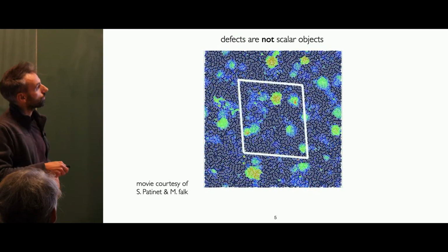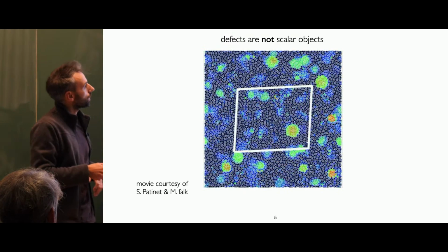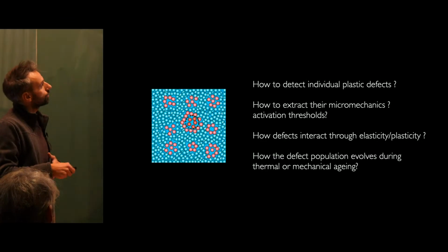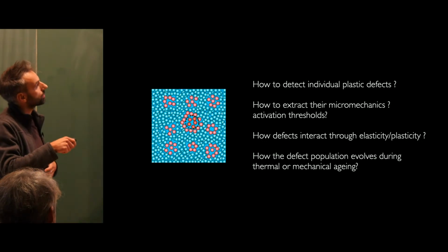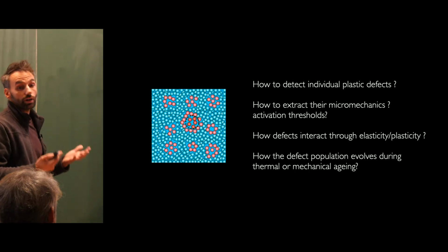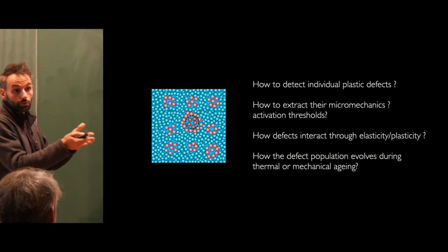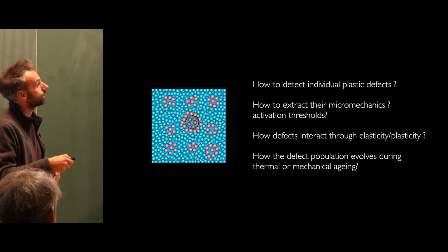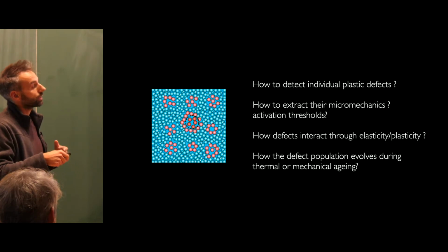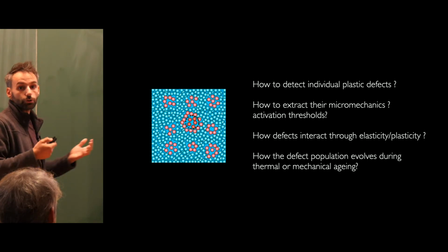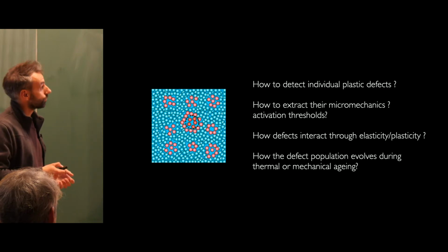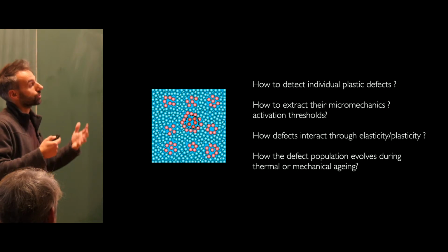So we will have to develop methods to find defects in glasses, maybe individual defects. As you see, that's localized plastic deformation, so you are looking at localized defects, not extended ones. How to extract their micromechanics, because it will depend on the deformation tensor that you apply in your system. Maybe if you're lucky, even activation thresholds.